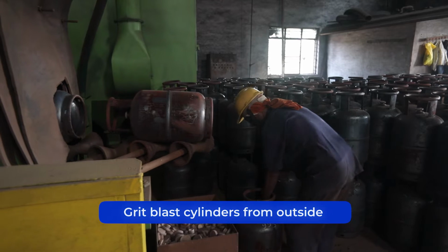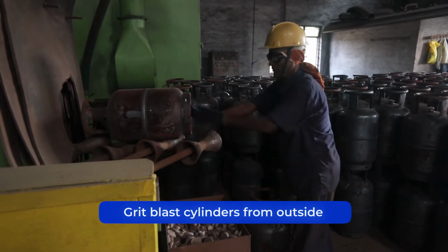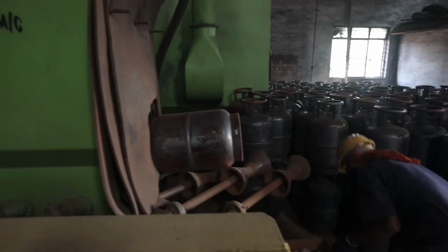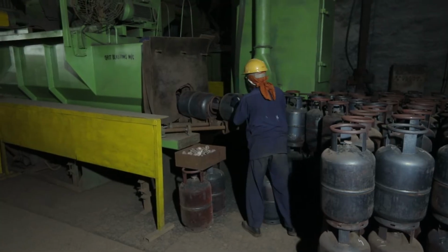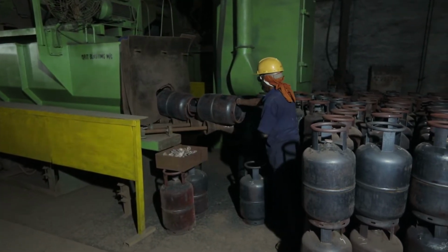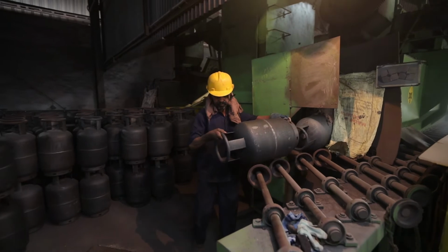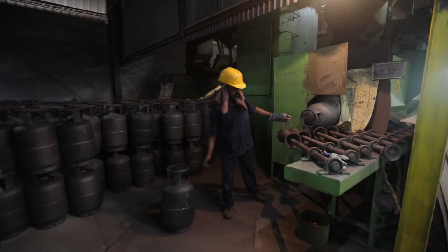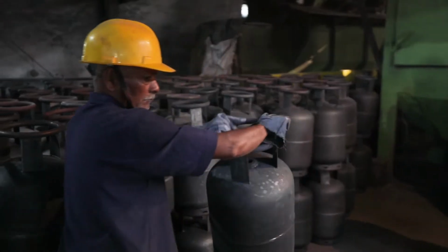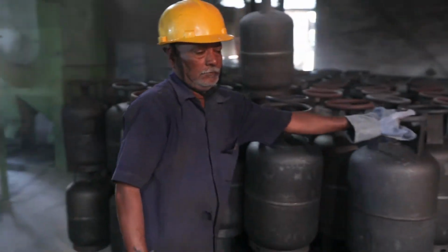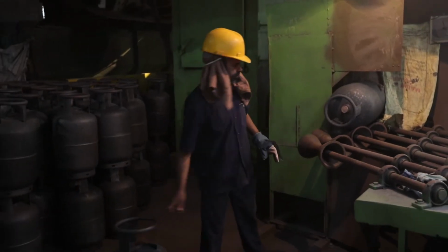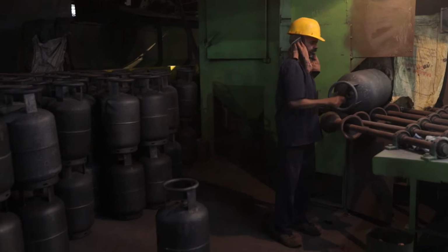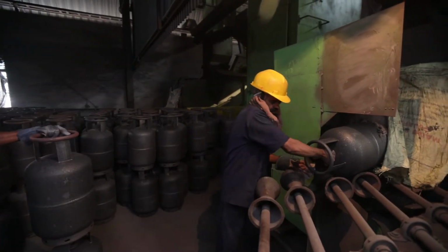The bung hole is now blocked with a plastic cap to prevent grits from entering the cylinder. Cylinders are now loaded on the conveyor of the grit blasting machine horizontally. The iron grits are blasted on cylinders centrifugally to remove outside scales. After this, the grit blasted cylinder will have a clean rough surface of 2.5 SA specification.